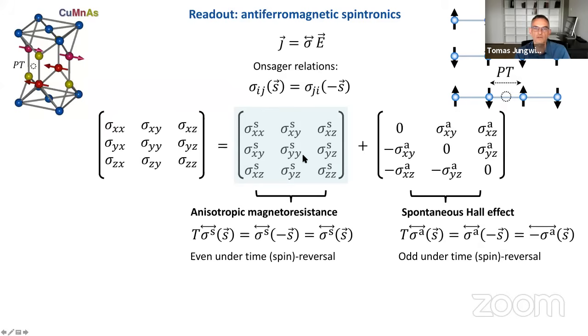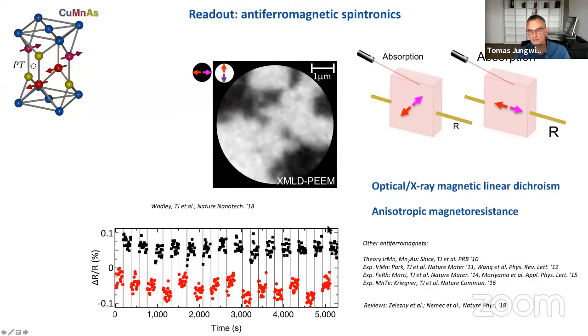tensor components of the conductivity or resistivity, but that's okay, because anisotropic magnetoresistance, the fact that it's been used in ferromagnets for many, many decades to sense the changes in magnetic order, is part of this symmetric or the ordinary conductivity components of the conductivity tensor. So anisotropic magnetoresistance can exist in any system, including these PT symmetric antiferromagnets, and in principle in any antiferromagnetic system.